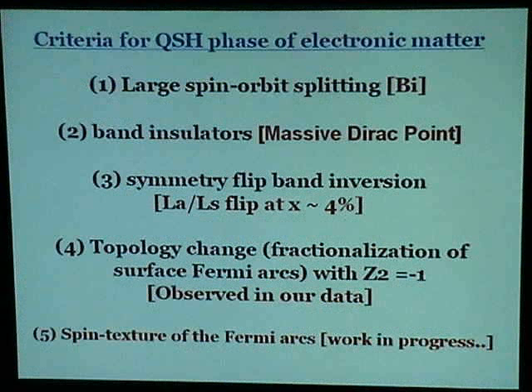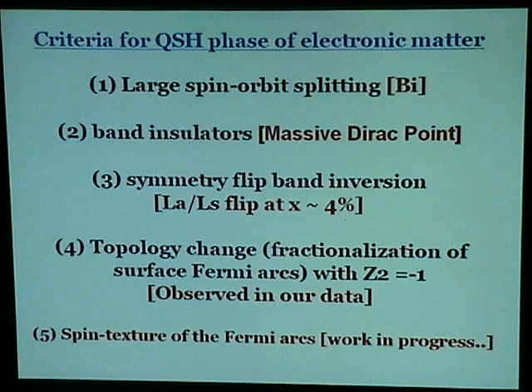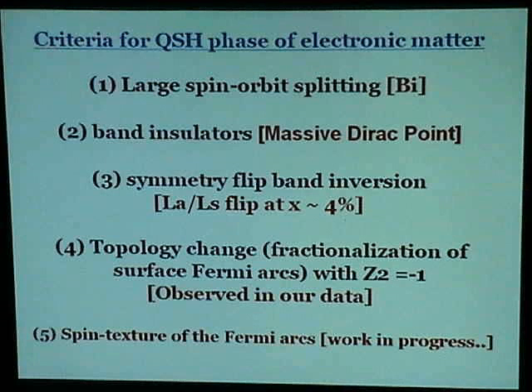So here are the hard numbers. Band insulator — we isolate the massive Dirac point. You can fit it with an equation like this. And M is a function of X. So we have not located the Dirac point, but based on our band systematics, we believe we know where the real Dirac point is. The final thing we want to check is if there is spin texture on the Fermi arcs, which can be done with circularly polarized light photoemission. This is a work in progress.